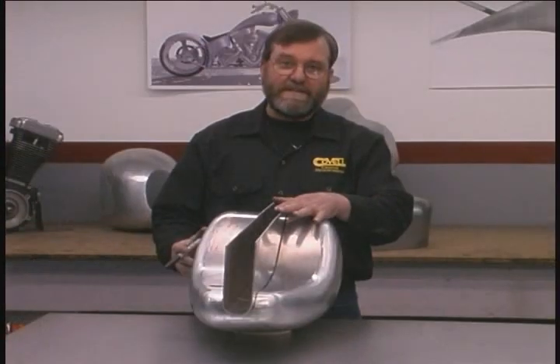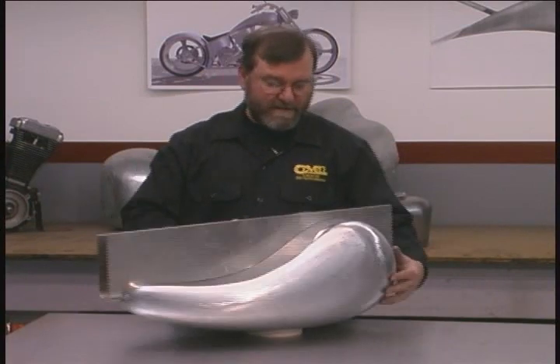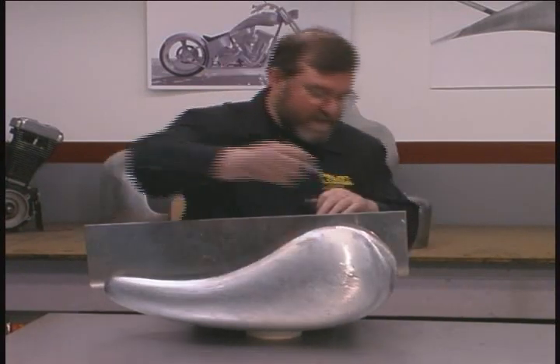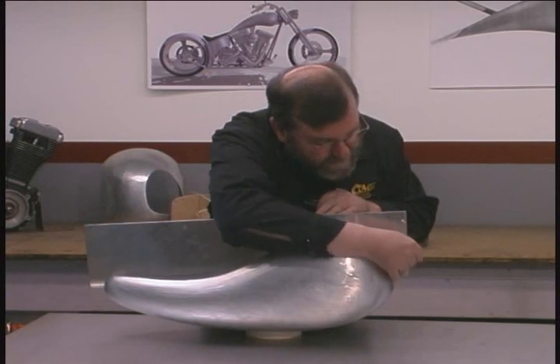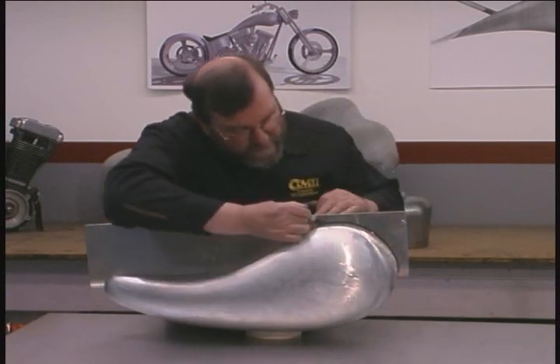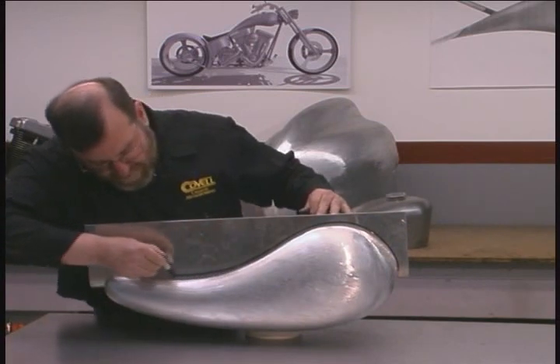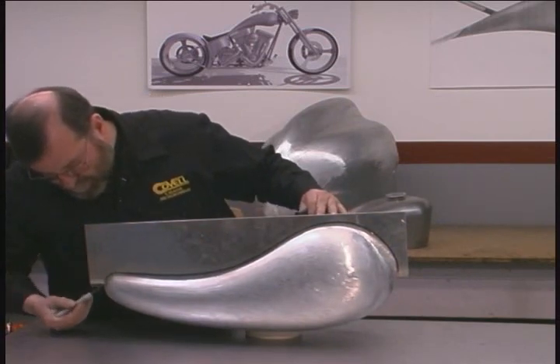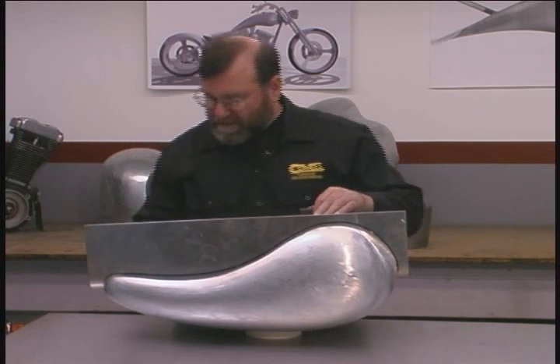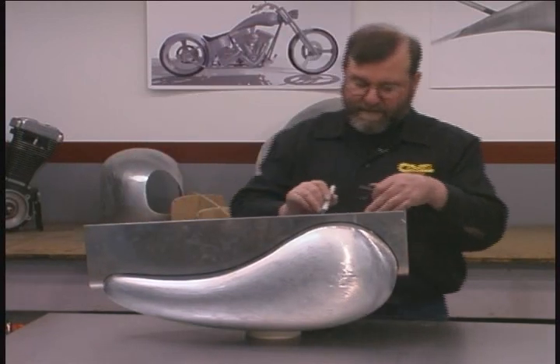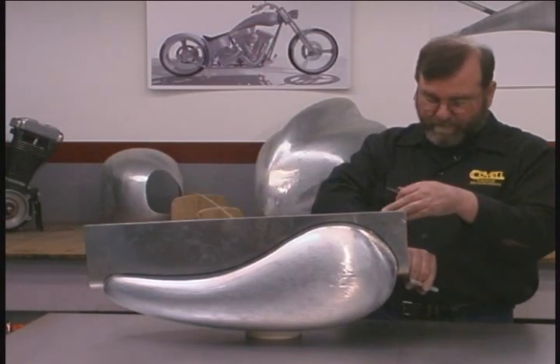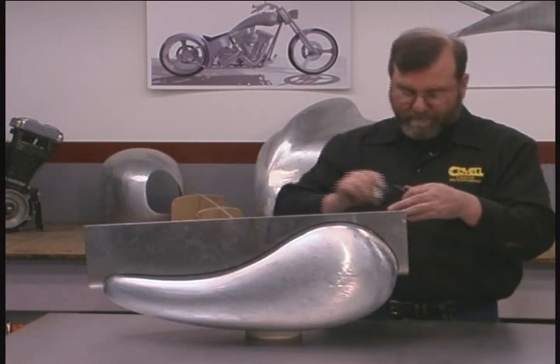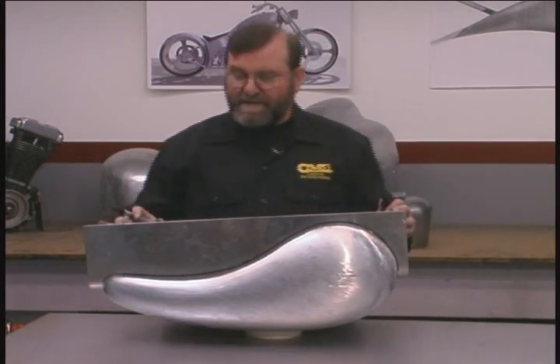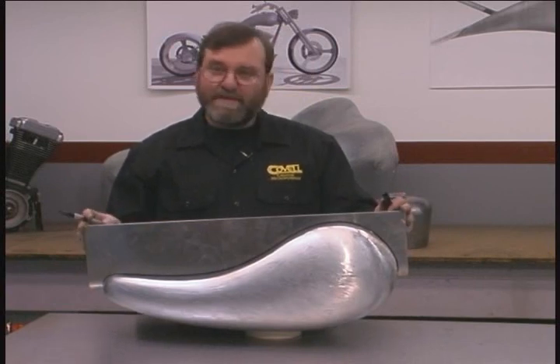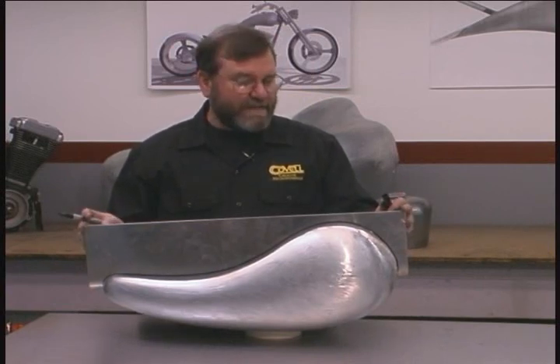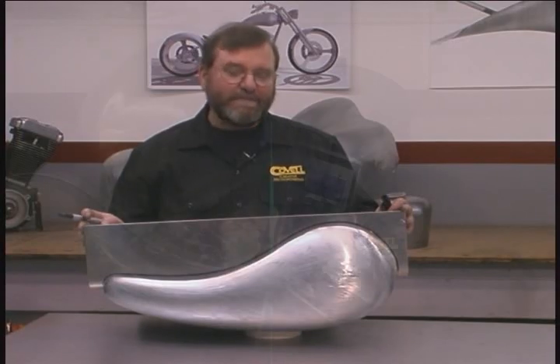The tunnel is put into the tank now, and we need to mark it for trimming. So I'll use a felt tip marker and simply trace around the edge. And this will give us the line to trim on. Eighth-inch material is too thick to cut with hand shears, so I'm going to use a bandsaw to do the cutting. If you don't have a bandsaw, a saber saw would work as well.